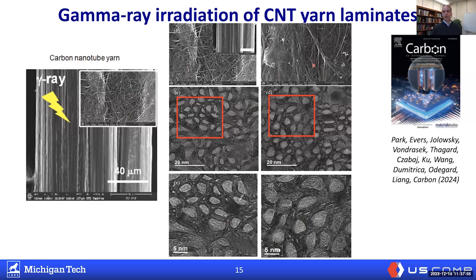And what's interesting here, if you're looking closely, trying to figure out the differences, you're not going to see them. And that's the whole point of this figure, is that the gamma rays do go in, they do their job, but they don't completely destroy the material, as you may be afraid they would do. In fact, their effect is somewhat subtle. We can get it on other characterization techniques. We can see that it actually forms little molecular crosslinks between the carbon nanotubes themselves, or crosslinks between the carbon nanotubes and little pockets of amorphous carbon that are also present right here.